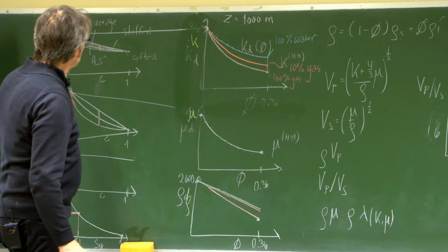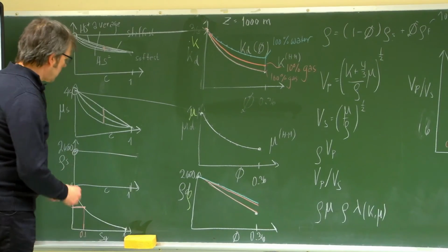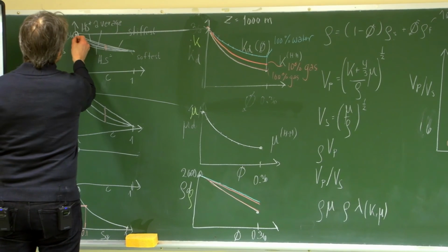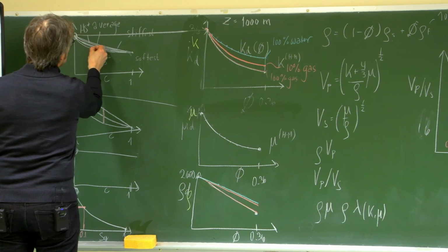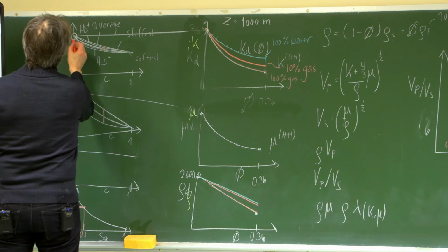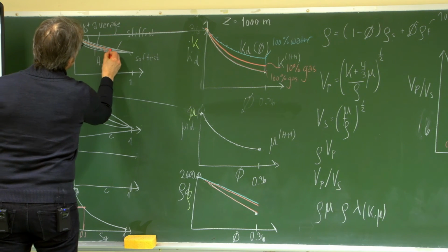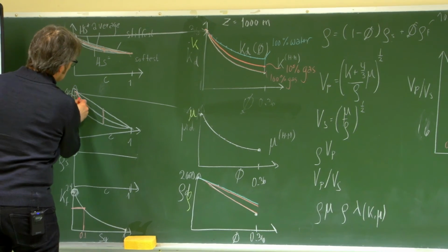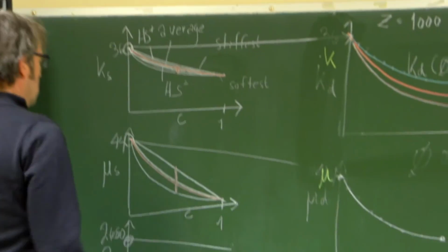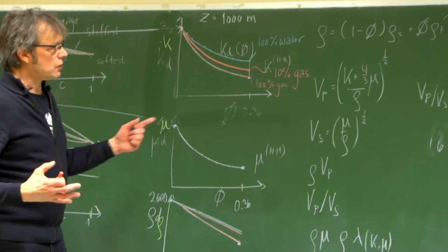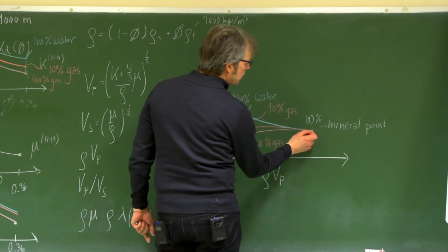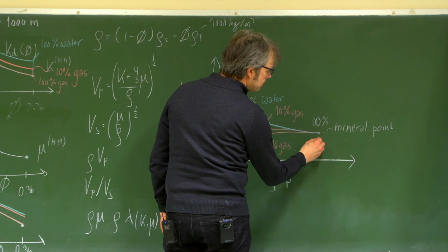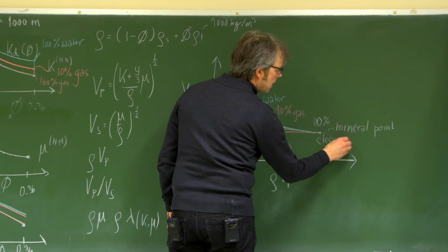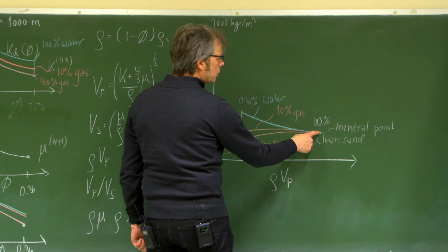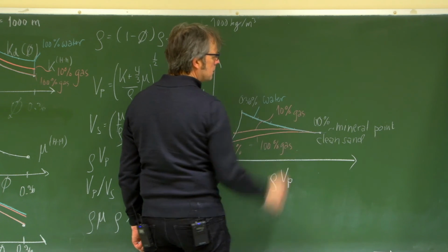If I did the same, just say that I assume, let's say, a Hill mix here, which is the line in between here. Midline, I can make it even red here. Same here. Then, if I did the same as we just have done now, I would see that my mineral point would move. So this is clean sand, remember? My mineral point would move in that direction, away.